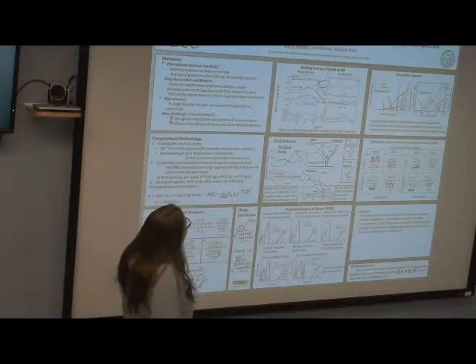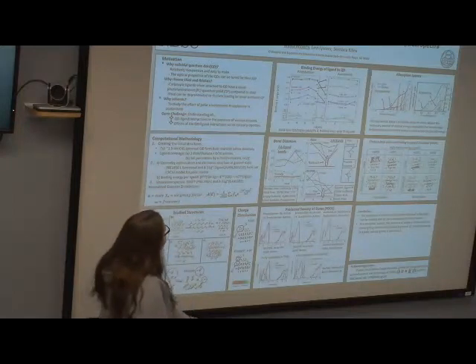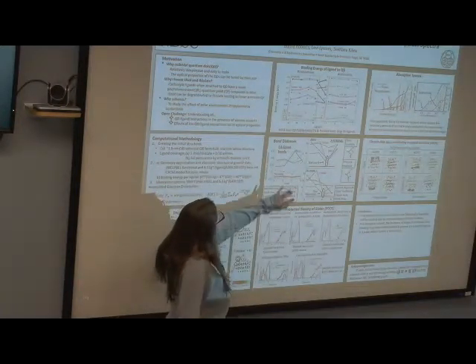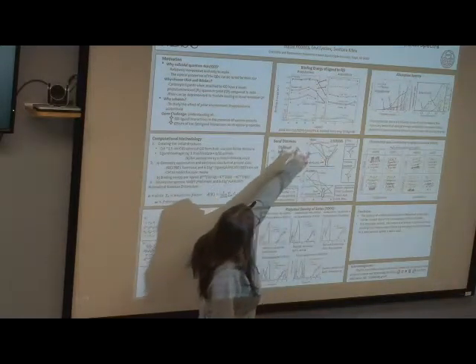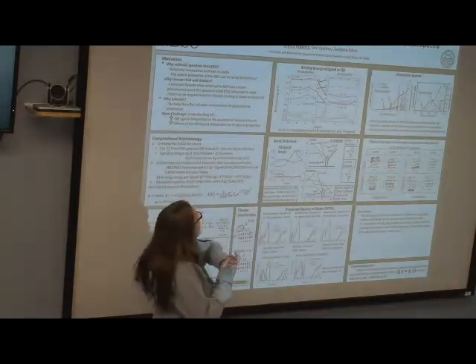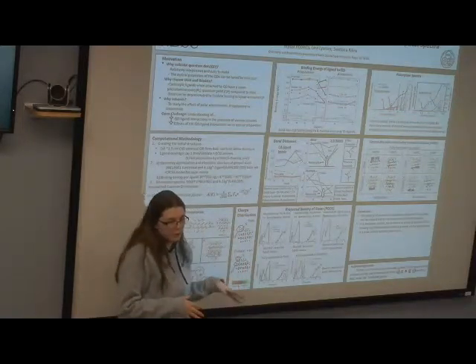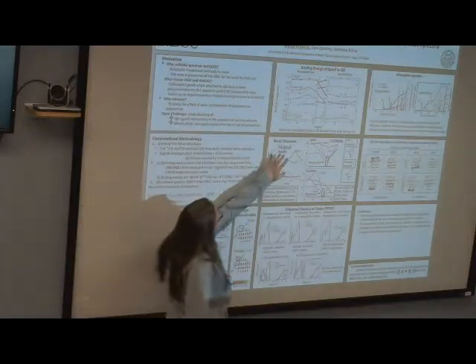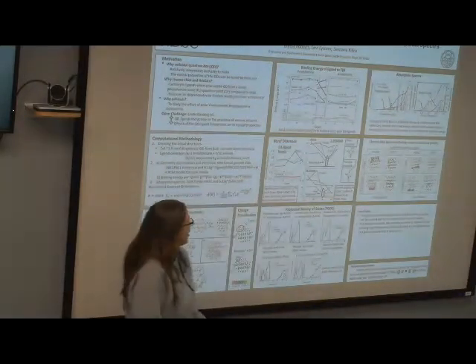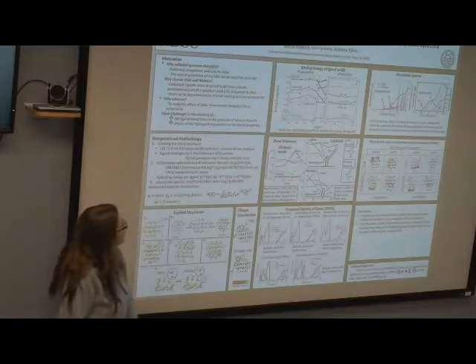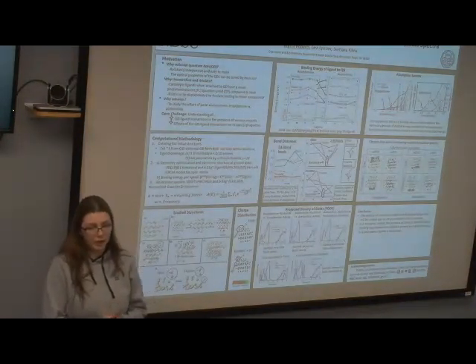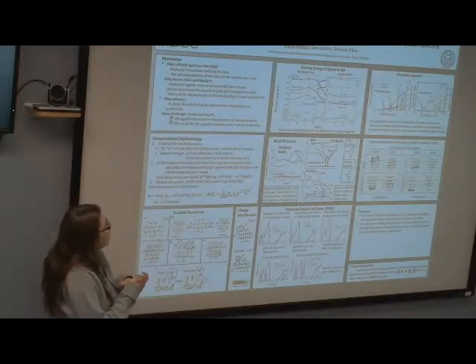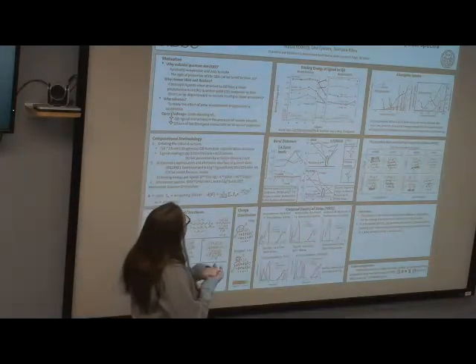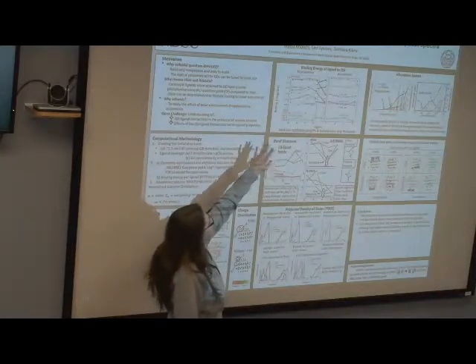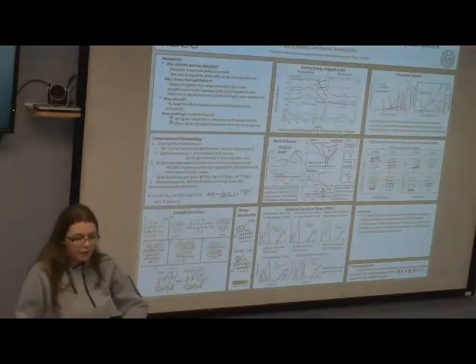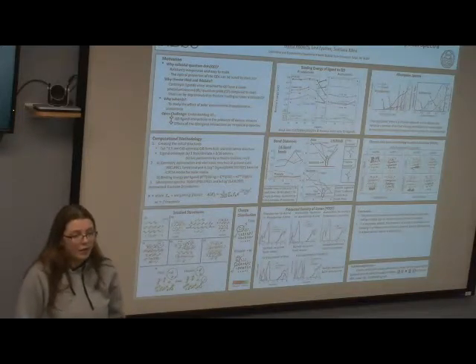Okay, and then I have my binding energies for the ligand to the quantum dot. All in all, acetonitrile generally moves up the binding energy so it's less negative by about 0.5 to 1 eV depending on what it is. But the neutral thiolate plus the proton, so this system here, is pretty much unaffected no matter if there's amine or no amine on the quantum dot, or which solvent it's in. But the negative thiolate and the neutral thiol are both severely affected by the lack of amine in acetonitrile.